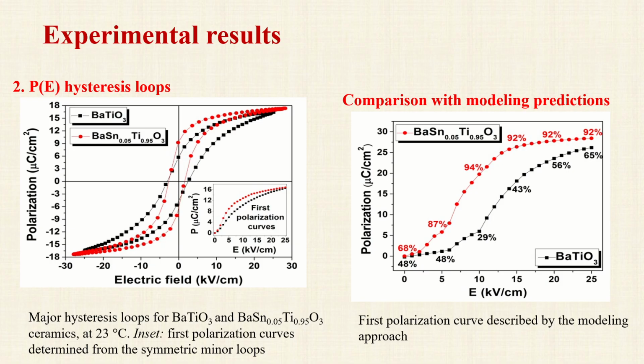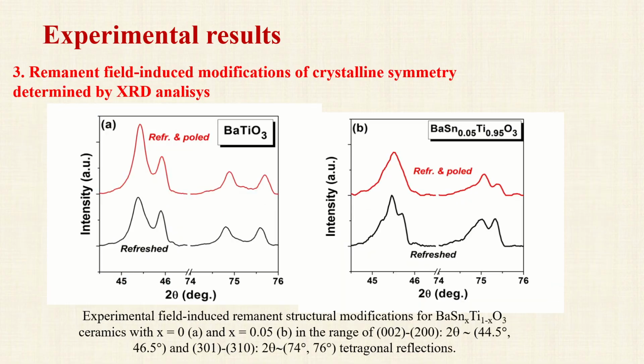Very remarkable is the comparison between the first polarization curves determined by the experiment and predicted by the calculations. The doped barium titanate presents a more rapid increase of the polarization at low applied field values, but better saturation at high applied fields. Unfortunately, the peculiar values of the concentration of the phases at intermediate applied fields could not be demonstrated yet by experiments. However, we are able to analyze the phase superpositions in unpoled and poled samples by X-ray